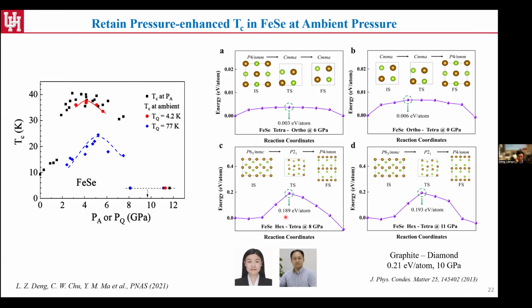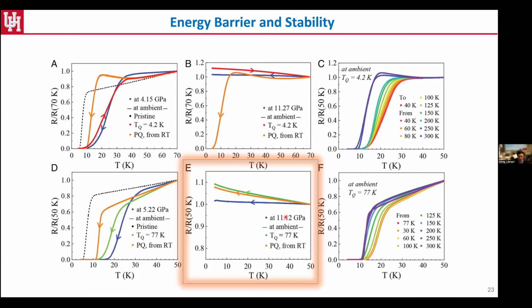So this also tells us we expect the hexagonal phase to be more stable than the tetragonal phase locked in at ambient condition. And that is surprisingly also consistent with what we saw in experiments. I do want to point out these very interesting results here, even though it's non-superconducting. From a superconductivity point of view, it may not be that exciting. But the exciting thing is we're able to warm up all the way to room temperature. I'm not showing the whole curve here, but this hexagonal non-superconducting phase, once retained by quenching at 11 GPa, was able to do the thermal cycle all the way up to room temperature and back again, and it still remains non-superconducting. So that also demonstrates how robust this pressure-quenched phase is, right?